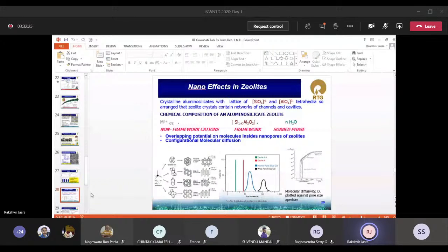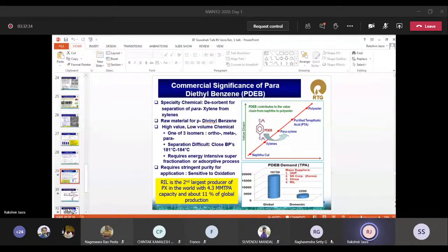And by exploiting this concept, we developed a catalyst for making paradiethyl benzene from ethyl benzene, or a mixture of, let's say, C8 aromatics, ethyl benzene, metaxylene, everything is there, but we want only ethyl benzene to react and give paradiethyl benzene. And paradiethyl benzene is a very important chemical when we make polyester. Polyester needs paraxylene, and paraxylene production needs para-DEB, because paraxylene is separated from C8 aromatics by an adsorption process, and for desorbing the adsorbed paraxylene you need para-DEB. So this is also very important. We want to produce para-DEB, and as I said, we are the second largest producer of paraxylene in the world now, and that's why this material is important to access. We produce around 4.3 million metric tons per annum. 11% of the world capacity of paraxylene is within Reliance, which is very important.